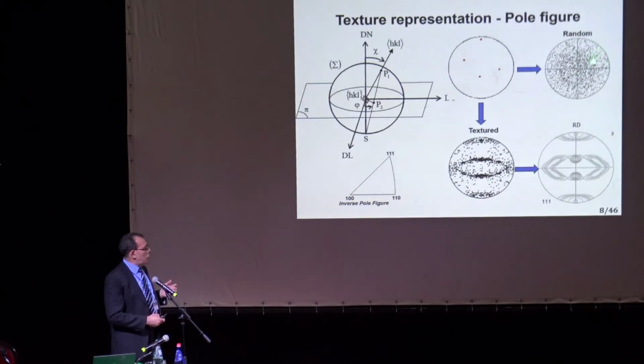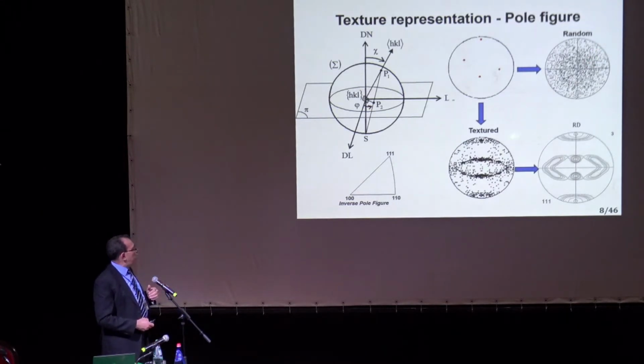So I know exactly where the crystal sits with respect to macroscopic axis. This is a direct pole figure. And this is a textured material. This is a rolling texture. As you can see, this is random. This is rolling. You can see concentration of orientations in specific areas. That means we have preferential orientations.